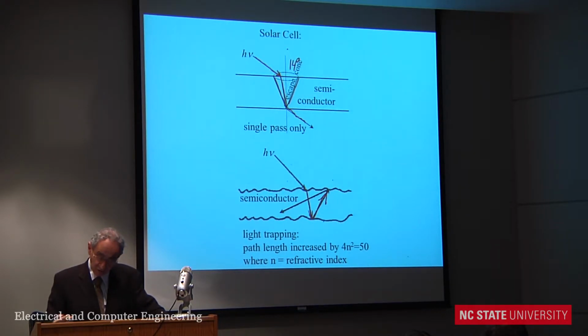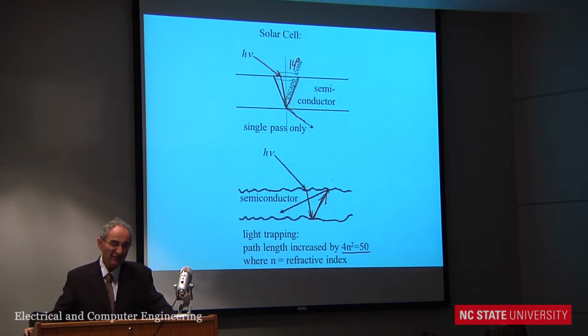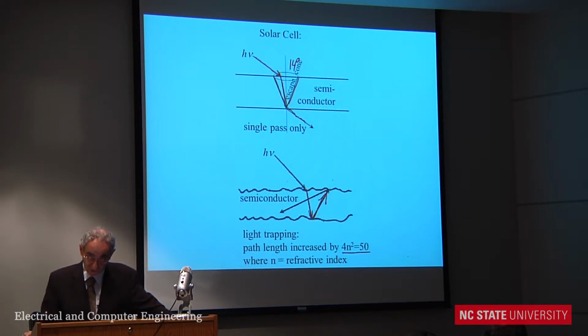In fact, you can go through some little reasoning, and you can prove to yourself that it bounces around and increases its internal path length by 4 times the refractive index squared. Now, index 3.5 squared is 12, times 4 is 50. So the internal path length in the semiconductor is increased by 50 times. So that's huge. It means you're using 50 times less material. So that's very enormous and very surprising.